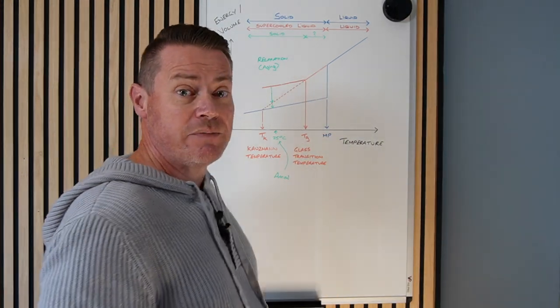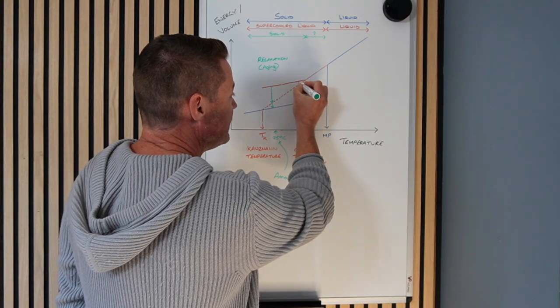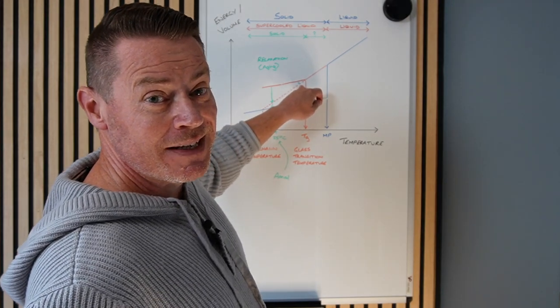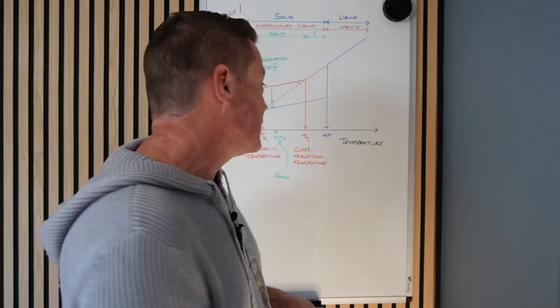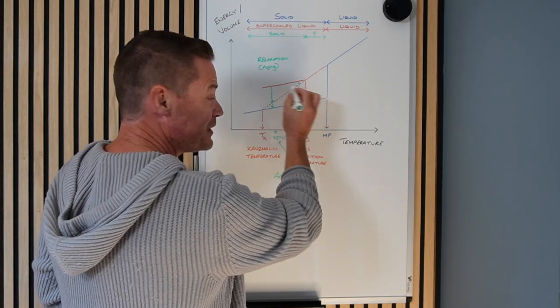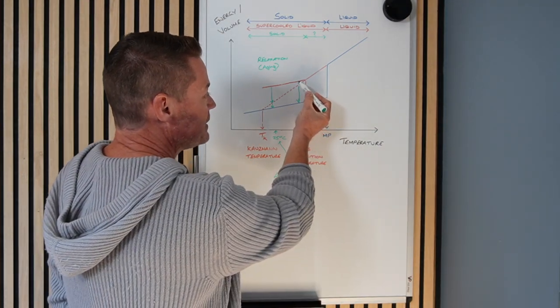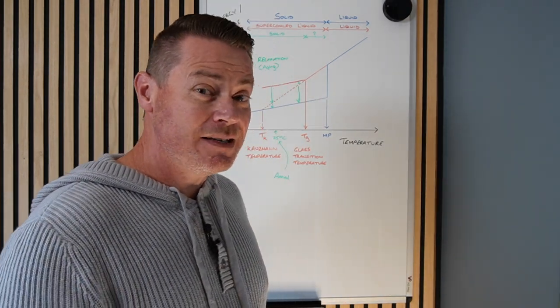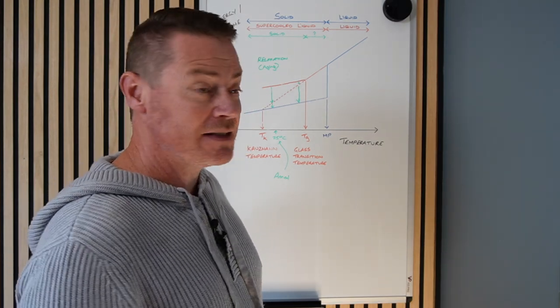But I hope you can see that if we have a material with a glass transition temperature here and we were to anneal it at a temperature very close to its glass transition temperature, then as it loses energy upon annealing, it doesn't have to lose an awful lot before it would touch this line. And once it's got to this point, the propensity for it to crystallize is going to be a lot higher. So in principle, this bit is quite slow, but this bit is quite fast. So if we stored our glass very close to its glass transition temperature, the relaxation has only got to go for a little bit before it suddenly is able to crystallize. And that's why amorphous materials stored close to the glass transition temperature are quite unstable and tend to re-crystallize.